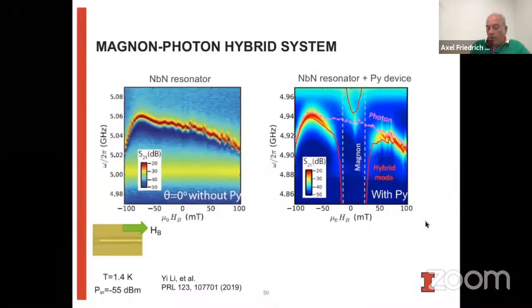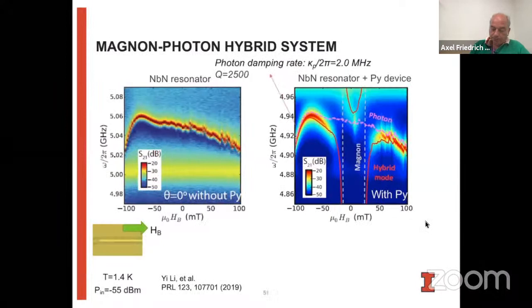Now, when we have the permalloy in there, we see that there is a strong mode splitting at the point where the magnon excitation crosses the excitations of the photon resonances in our system. So we see a mode coming down here, and we see an additional mode on the top. We can get the photon damping rate by being far away from this crossover point. We see that now the damping rate is 2 megahertz instead of the 0.5 megahertz that we had earlier. So just simply having the permalloy device integrated into the resonator deteriorates the properties of the resonator to some extent.